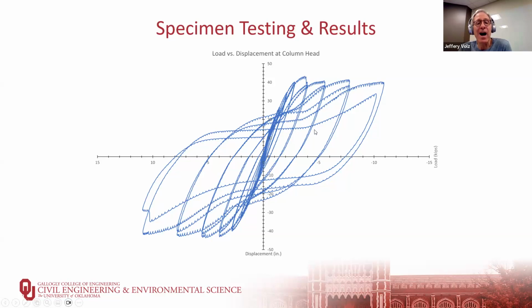It wants to straighten out. Then you start having an increase in capacity. So that wrinkled, if you will, steel tube is now stretching out when it's in tension, and then you continue to increase in capacity because the steel tube is still there, and in tension, it's not buckled anymore. But then you go back in the other direction, right? You start reversing the flow and you come back in the other direction. And again, you buckle the steel tube that's now in compression, and you start to straighten out the other opposite side of the steel tube and pick up load.